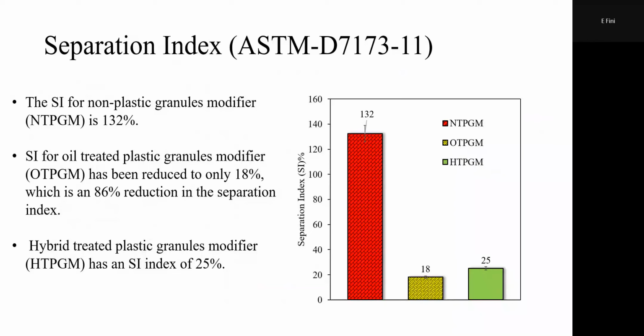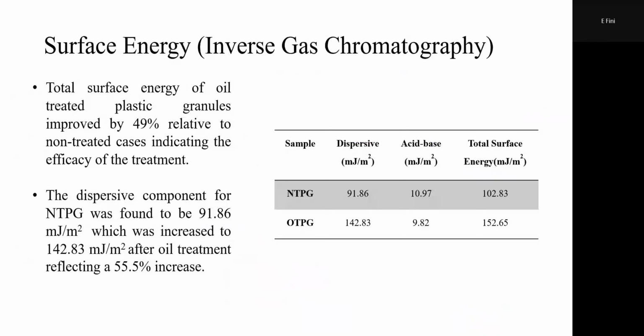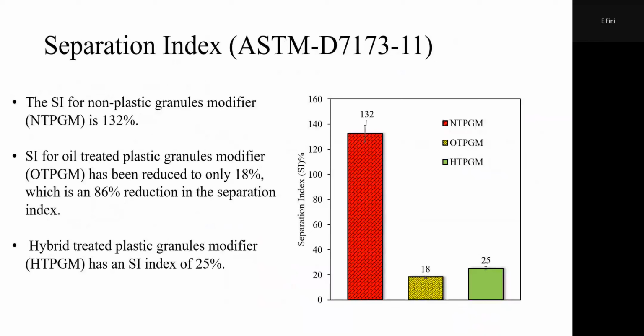And in the case of the treated one, we reduced it to 18%. Still they separate, but not as badly. And in the case of the hybrid treated one, it is 25. So we do have a threshold in the standard specification for pass or fail. Literally all bitumen, because bitumen is not a homogeneous material to begin with, does phase separate a bit. So there is a threshold for what can be accepted and what cannot. 132 is definitely a rejection. So in this case, we improved the surface energy. As a result, they like each other better and they separated less.